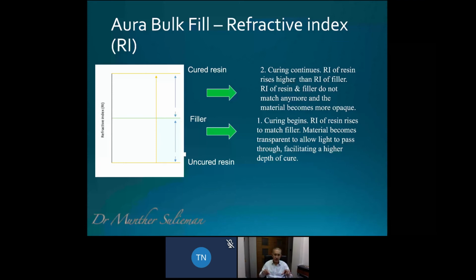If you recall a few slides before, I said to you, different manufacturers use different methods to ensure a depth of cure. So what SDI do here is they use different resins, and when you have uncured resin, the refractive index of these resins is matching the refractive index of the filler content to start with, and as they cure this product, the refractive index changes. Don't ask me how it changes, but they assure me that it changes, and then by the end it doesn't match anymore, hence you get the aesthetics back, but by that time you've cured all the product all the way down to the end.